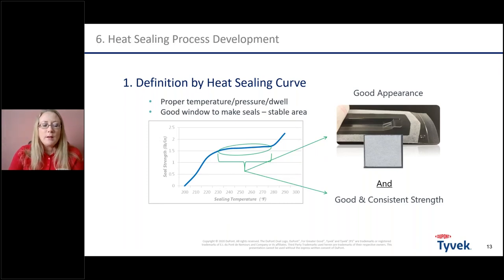So there are different ways of defining the sealing process window, which I will just shortly raise here. So, for example, heat sealing curve assessment. You can, for example, fix dwell time and pressure first, and then seal at different temperatures, starting from a lower temperature up to a higher temperature in steps of, it depends, right? But let's say in steps of 5 degrees Celsius or Fahrenheit, and then you go up and you look at what your seal strength is doing.